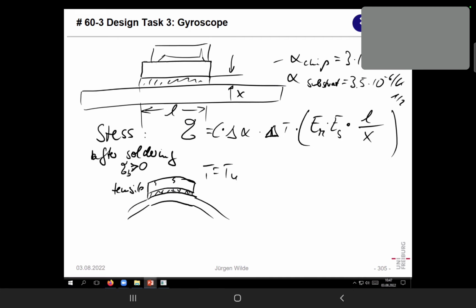After the soldering. So about the data. We have also seen the delta alpha is 0.5 times 10 to the power of -6 per Kelvin. What is a delta T? That would be at room temperature here. So it's 240 minus 25 degrees centigrade. And temperature differences are given in Kelvin. And so it is 215 Kelvin.